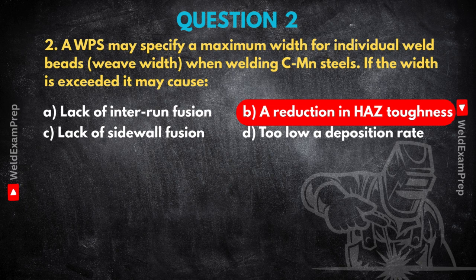Okay. So this coarse grain structure in the HAZ directly leads to lower toughness. The steel in that zone becomes more brittle, more likely to fracture under stress, especially maybe in cold temperatures or under impact. It creates a potential weak spot. That's a great analogy, the wood grain. Makes it very clear.